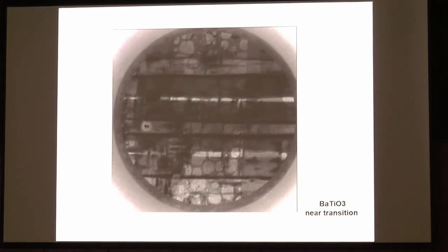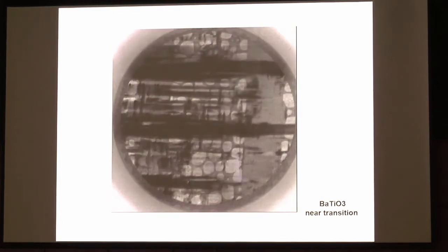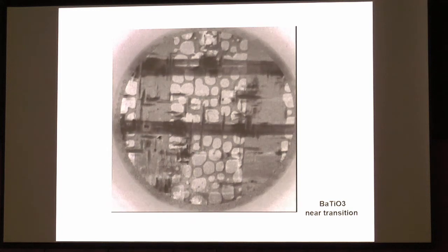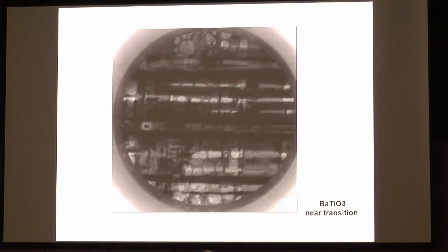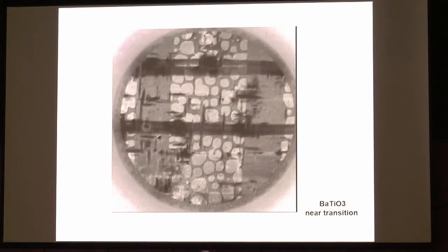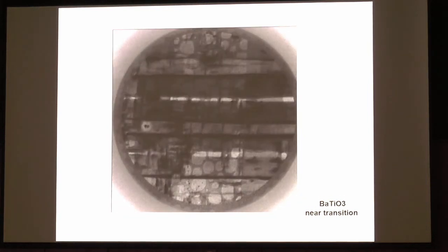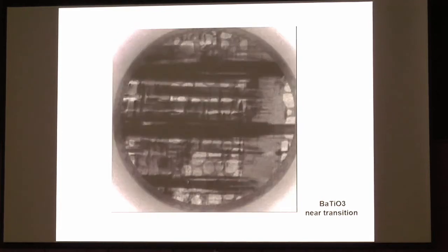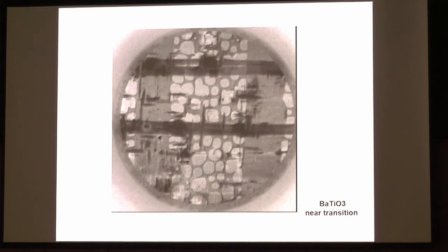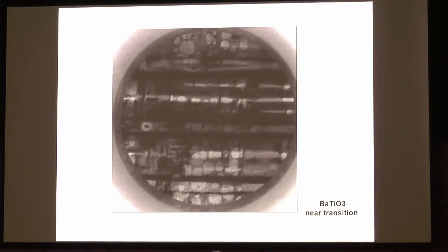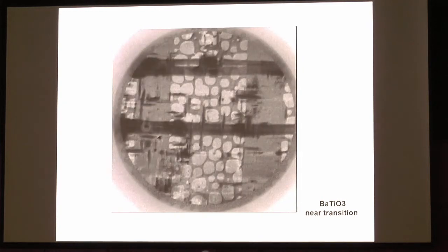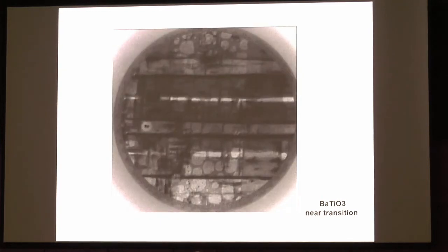Now, when I was a student, we always learned that there's a phase front there, and the phase front moves in a continuous way. Now, if you actually measure, then you see they're not moving in a continuous way, but you have the entire pattern formation thing we learned from Hohenberg and other people, which happens here. You have period doubling, you have the forking of domain boundaries, you have all sorts of things happening there, and it's happening in a jerky way. I mean, there's something happening here, then there's something happening there, and so forth.